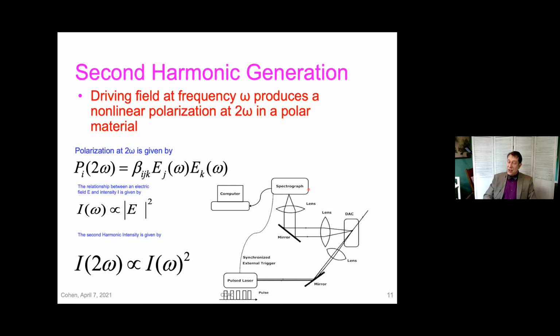Whereas X-rays do not show this. So in standard X-ray diffraction, the X-ray diffraction process adds center of symmetry back in. And so you cannot do a conventional X-ray experiment to see whether something is centrosymmetric or not. Whereas doing a nonlinear optics experiment gives you a straightforward way of looking for center of symmetry.